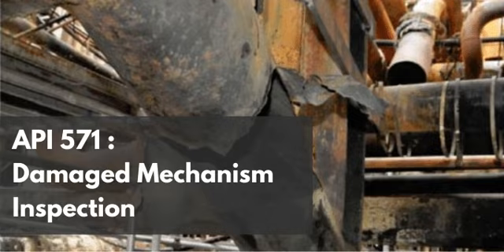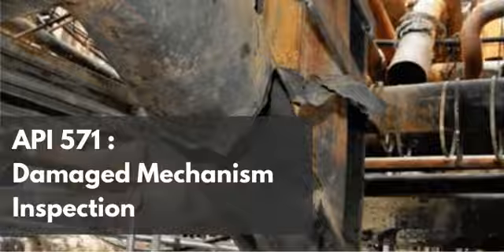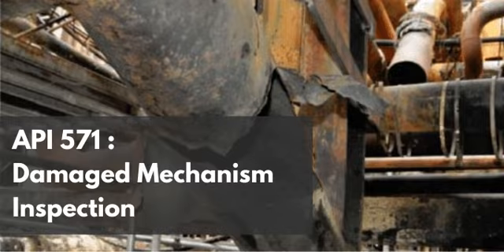Exactly. And what is sitting directly against the bare metal? A thick, solid layer of pure carbon coke. Yes. You are effectively baking the carbon permanently into the atomic matrix of the steel in your desperate attempt to get rid of the carbon on the surface. Wow. That is wild. So you managed to burn the coke off the surface, you clean the tube, your heat transfer improves, and you're sitting there thinking you've done a great job.